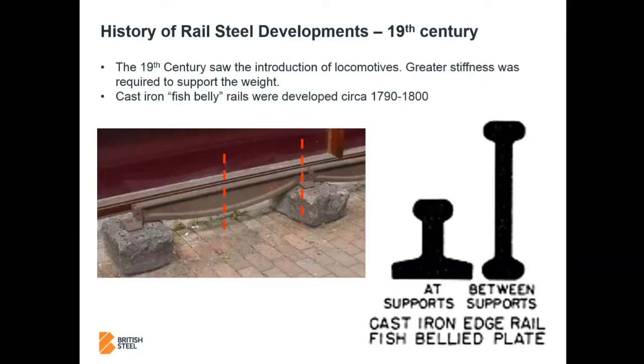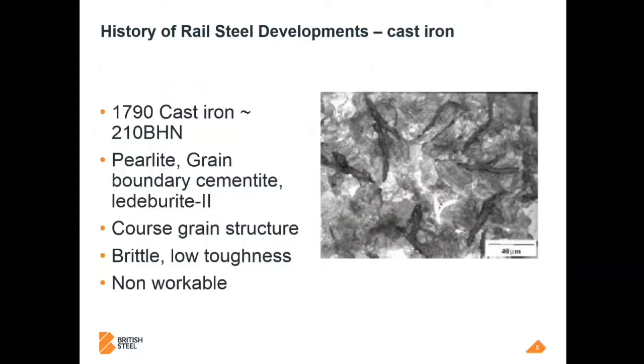Fish-bellied rails had a very short-lived life. Obviously, you need kilometers of track for even a modest railway, and individually cast 2 to 3 foot sections, it's not very economically viable. It's a very slow and difficult manufacturing route, and the material is not ideal. But it was the available technology at the time, and during the Napoleonic Wars, there were a lot of foundries making cannons, etc. So the technology was widely available, and that's why cast iron was the preferred material for a complex shape.